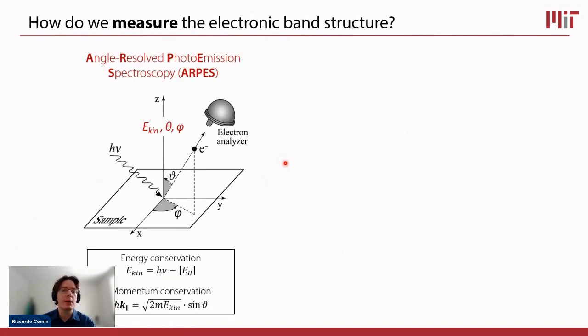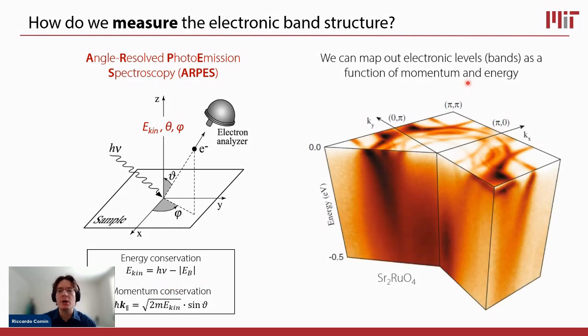So how do we measure the band structure? The technique we use is angle resolved photoemission. I presume most of you are familiar with this technique. It's a modern version of the photoelectric effect that was discovered by Hertz and explained by Einstein. So you shine ultraviolet photons onto a sample, you photoeject electrons, you collect these electrons in the so-called electron analyzer, which can measure their takeoff angle and their energy. And by simply applying energy and momentum conservation, you can map out the electronic levels or the electronic bands as a function of both momentum and energy.